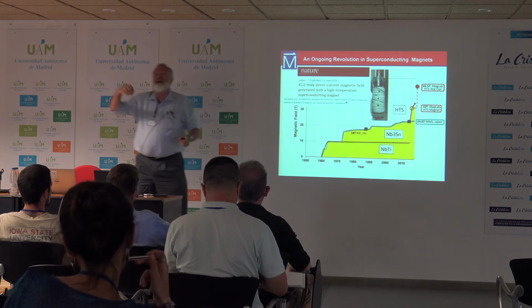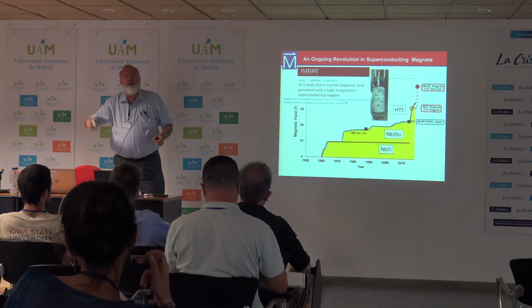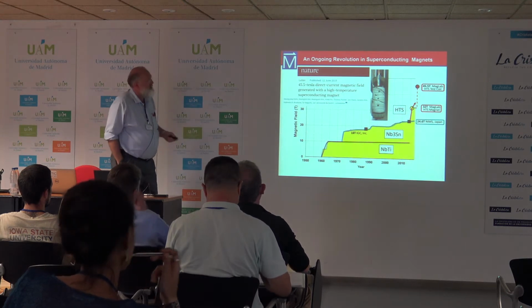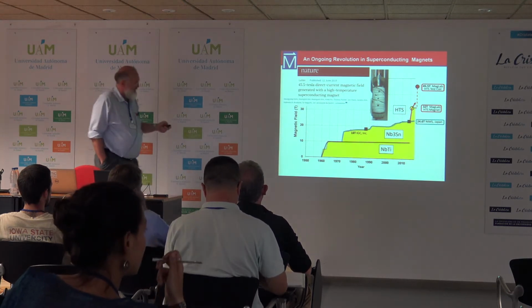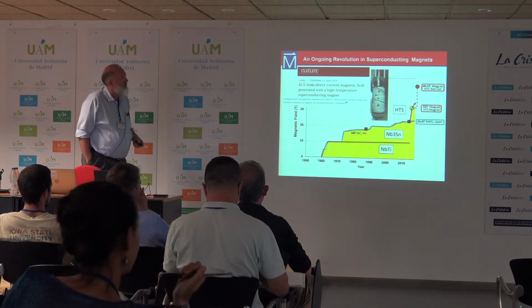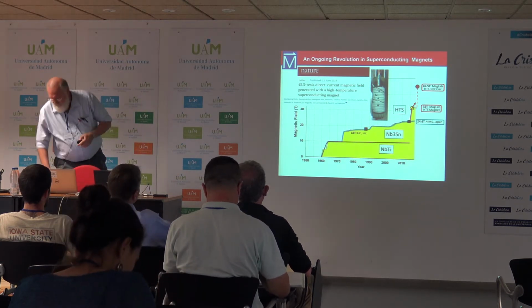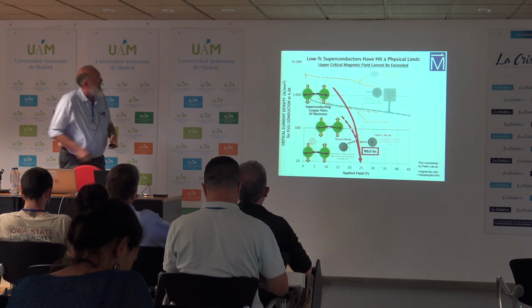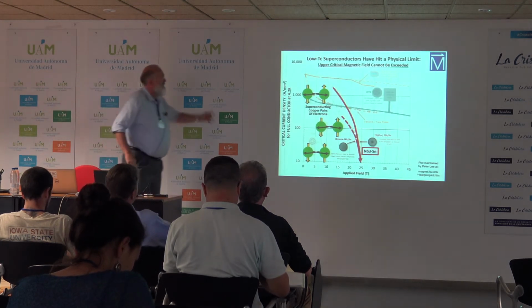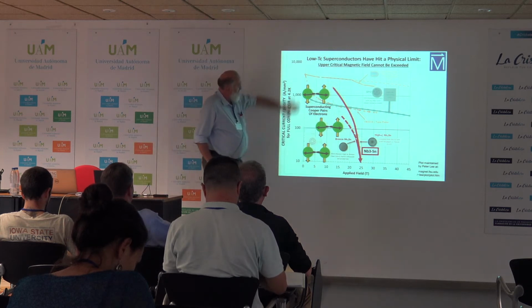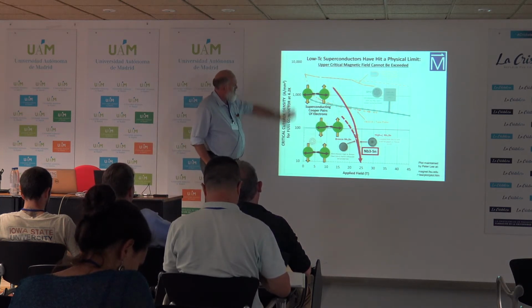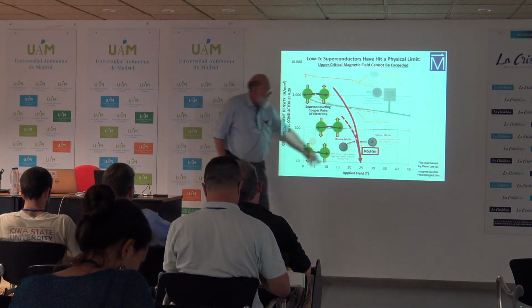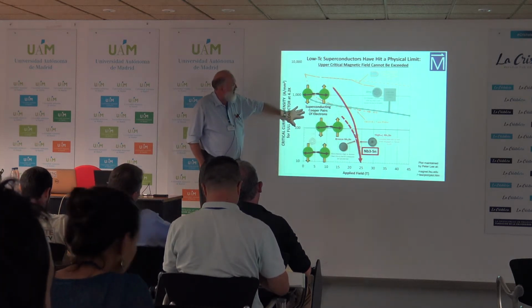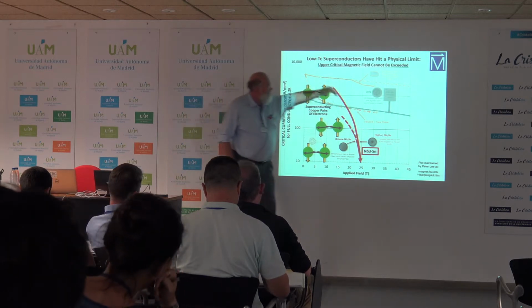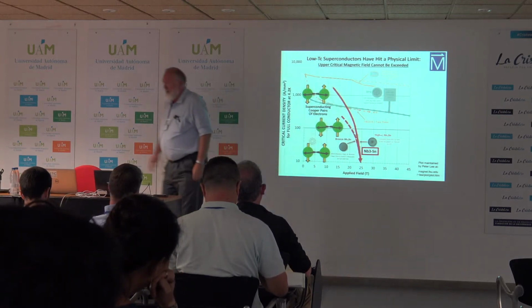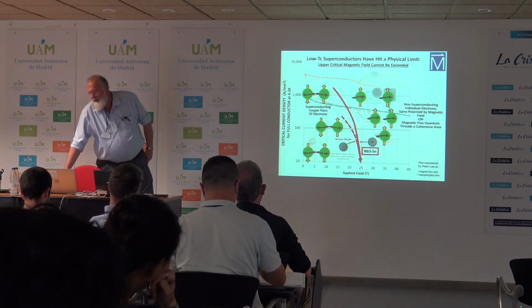We need to figure out quench protection, we need to figure out the stresses, and a number of other problems, but there will be very high field superconducting magnets in the coming decade or so. We're currently working on a 40 Tesla magnet, and I'll go to manual mode here. And in just the simplest schematic, if you plot critical current density, so not temperature, but critical current density on a log scale, and applied magnetic field, the ability for a superconductor to carry current dies out at some point due to the upper critical magnetic field. And the physics of that can be two mechanisms.